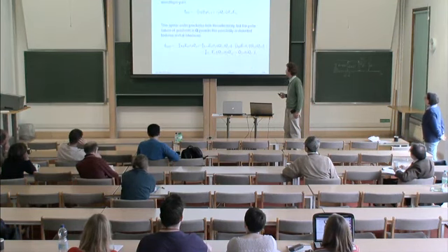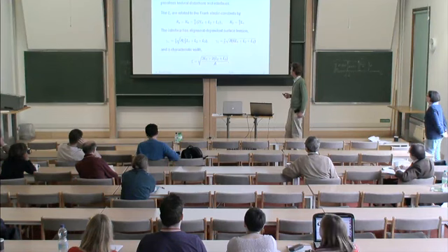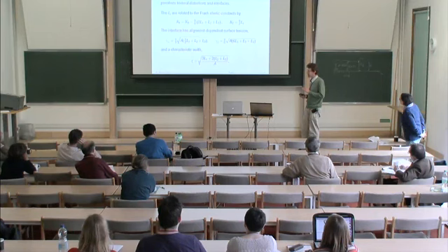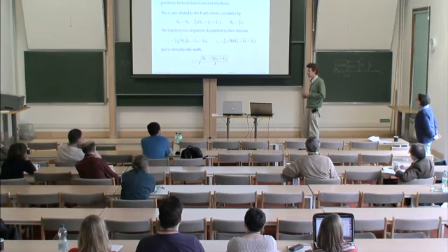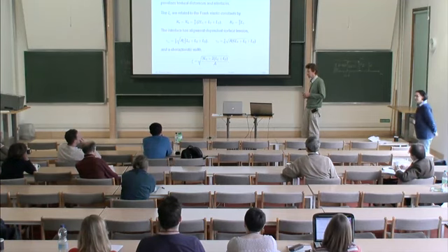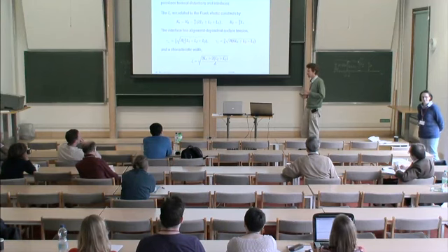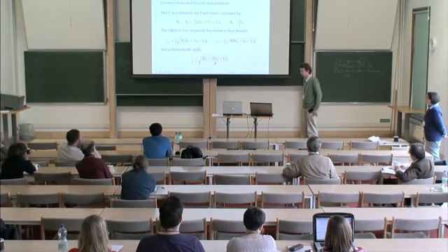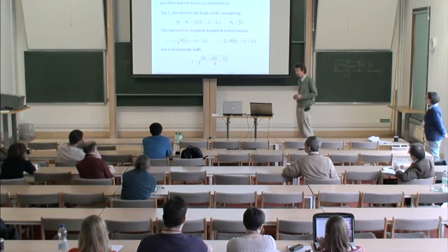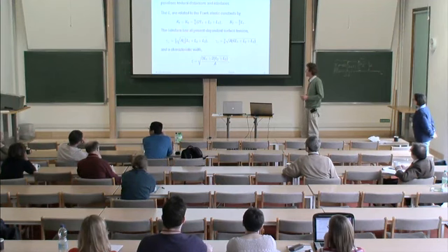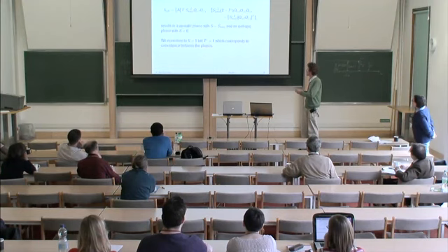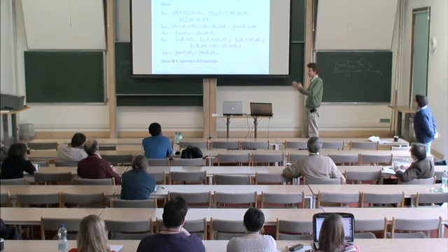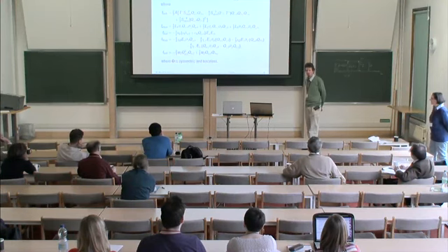We worked it out using the uniaxial approximation, and then you find that with L1 there is only a square gradient term in S, the nematic order, but with L2 and L3 there is a term which has dot products between the director and the surface normal, and the gradient of S. And the A comes in because we want to minimize the sum of the bulk and elastic, and that gives a trade-off which sets your width. It's a sort of natural boundary condition.